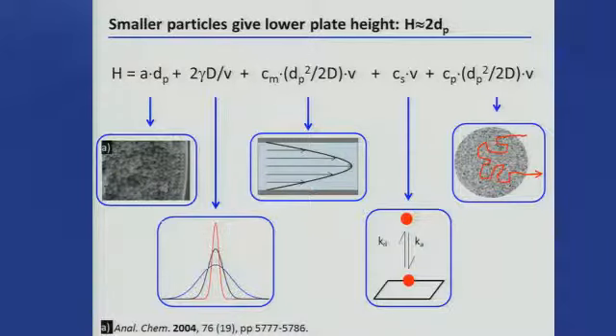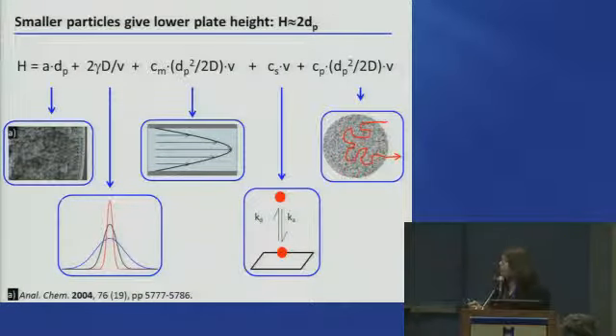And so the smallest particle size that's used in commercial chromatographic instruments is about 1.7 microns. And people who empty these out and measure them say it's really more like 1.9 microns. And so these are really tiny particles we're looking at. And most of what I do now is use 500 nanometer particles. So about a factor of 4 smaller, actually a little under 500 nanometers. So almost exactly a factor of 4 smaller. And so it should make these terms a lot smaller. And so I was able to convince NIH to make a gamble on this, and the gamble seems to be paying off.